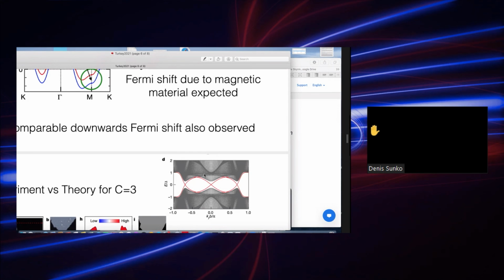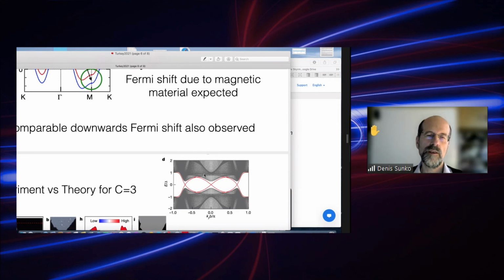I would just like to make a more general comment, from one theoretician to another. You have said that you have an effective 2D calculation, but as a matter of fact, that is probably all you need, because a student of mine and I have published a paper this summer where we show that the Hohenberg-Mermin-Wagner theorem is completely ineffective in 2 dimensions for superconductivity. The sample would have to be larger than the universe for the infrared fluctuations to suppress the order parameter. In other words, there is much more space for 2-dimensional superconducting fabricated materials than people ordinarily think, and I would like to encourage everybody to try to fabricate such materials. So this, I think, is a perfectly good avenue to start.